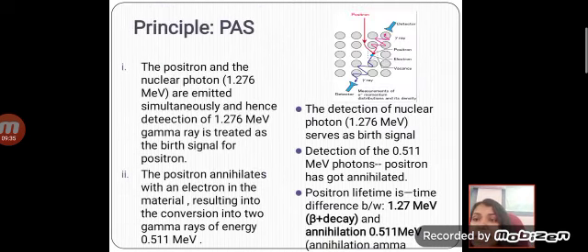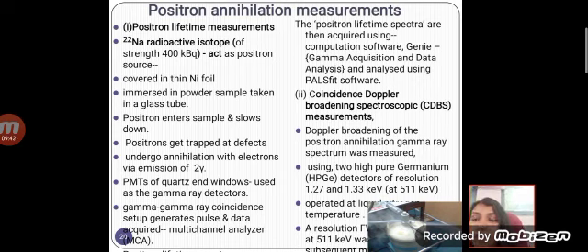So the principle behind this is that we use a sodium-22 radioactive isotope, which acts as a positron source, covered in a nickel foil, and it is immersed in a powder sample kept in a glass tube. So the positron enters the sample and gets trapped at the defects, which undergo annihilation with electrons via emission of 2 gamma rays. Photomultiplier tubes then detect and measure the gamma rays.